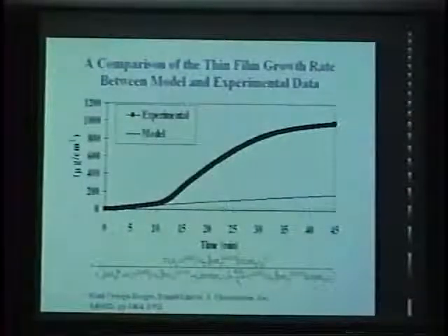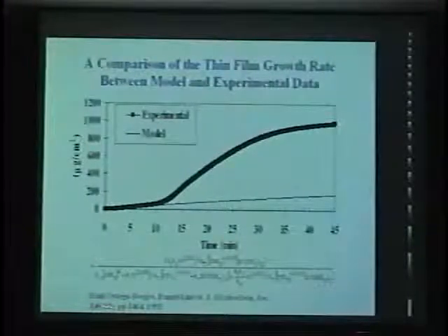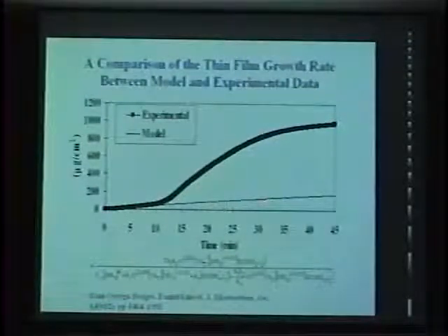Then there's a growth mechanism model published by the French group. So we use this model essentially just to try to reproduce and see if this model matches with experiment data. We use their reported K value, the reaction constant, and that fits pretty well for this linear growth region, okay. And since it's a molecular level growth model, it doesn't take into account the particle formation, so it can only describe this region.